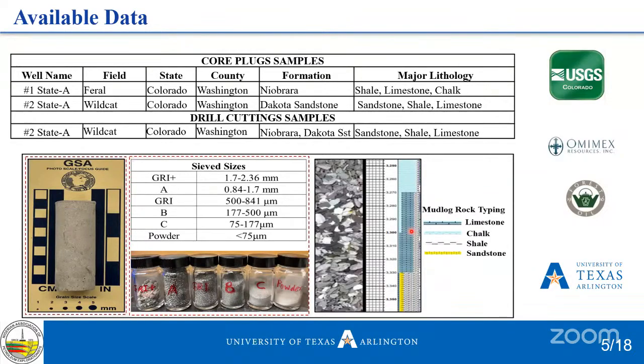And after I have done that, I had to clean it and do oven drying at 60 degrees centigrade for about 24 to 48 hours. And then I did my GSD, which is grain size distribution analysis, into different fractions. As you can see here, the higher size is a GRI plus. So these are the nomenclature I used, but these are the sizes from 1.7 to 2.36 mm to the least, which is the powder, and that is what you see here.